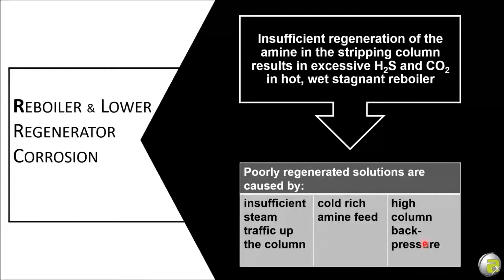So as far as all that corrosion that occurs in the reboiler and the bottom part of the regenerator, the big driver of that is the fact that you have not stripped inside the column itself. You have to regenerate inside the tower, not in the reboiler. And why does that happen? The first case is insufficient steam traffic up the column. You need to have enough steam that you have a proper overhead temperature. Typically that's over 100 degrees C as your overhead temperature at the top of that still.